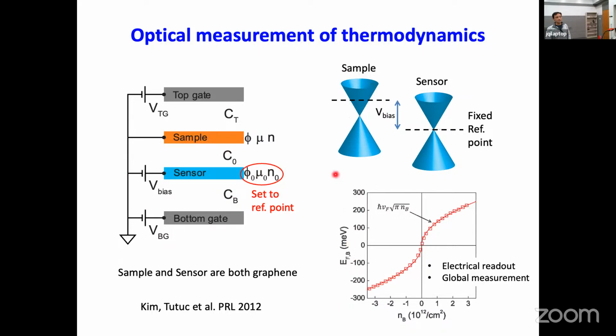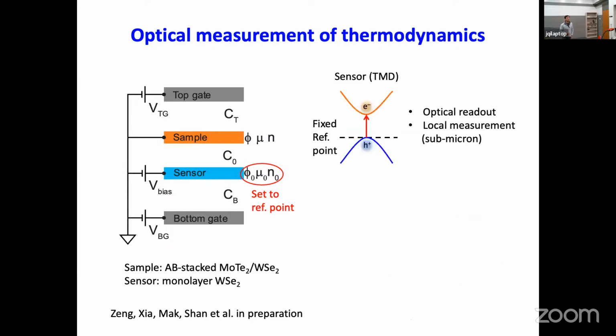And this is an example. You can see the chemical potential as a function of doping. In a monolayer graphene, you can see the characteristic square root dependence of the chemical potential with doping. It's a global measurement because it's an electrical measurement on the sensor.